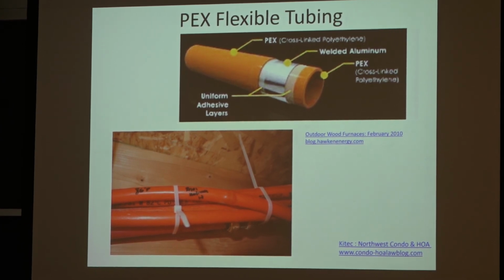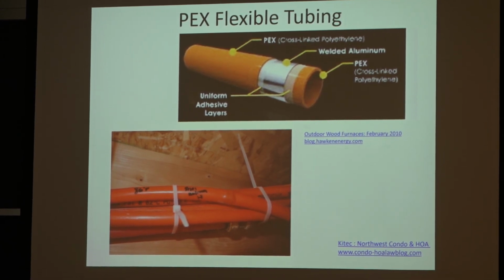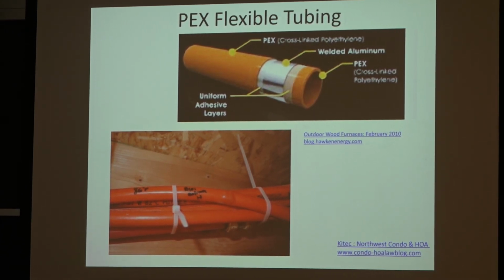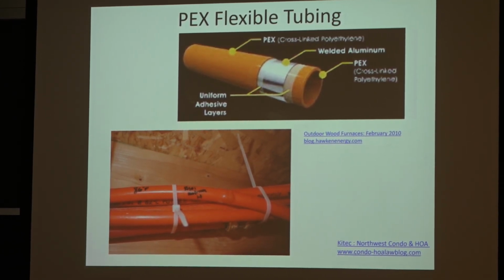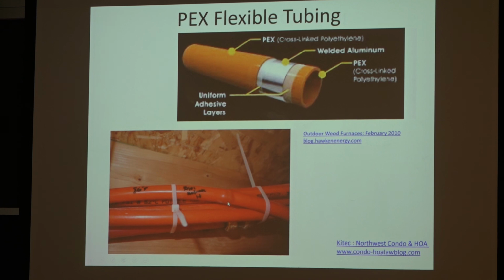And it's also very nice if you try to lay out these pipes under a floor, you're able to bend them and they'll keep the shape. So the plastic would want to bounce back, but because you have an aluminum in there, it's going to keep the shape. Now, in terms of application, one problem is the plumbers really like that type of pipe because they could get it into any shape they like very easily. So they started using it for potable water, which has oxygen, and the plastic was not engineered to resist oxygenated water on the inside. So you had accelerated degradation of the inside, corrosion of the aluminum alloy, and bursting all the way to the outside. And that happens in thousands and thousands of homes.